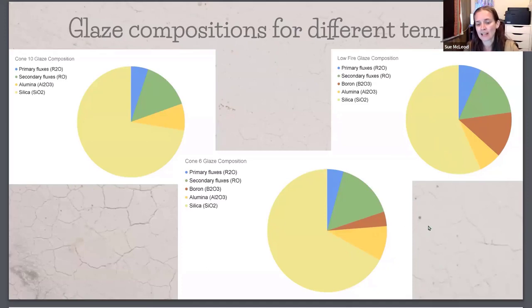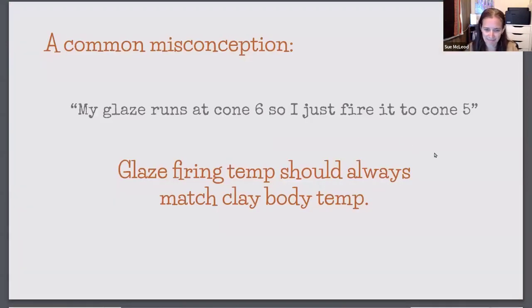So to lower a glaze's melting temperature, we either need to increase the flux, reducing the high melting temperature glass formers, or we need to increase the low melting temperature glass former, increase the boron, reducing the silica and alumina, or some variation of all of those things.